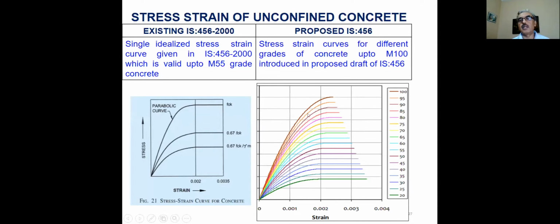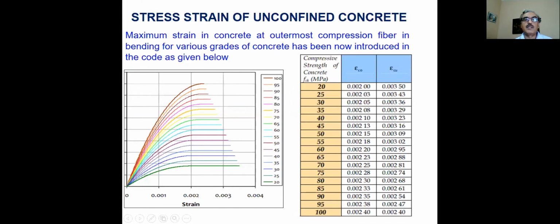If you go to M100, the curve becomes steeper, and there's not much difference between the peak and the ultimate, like we have here 0.002 and 0.003. There's a big gap for lower grades, but here at the top it is nearly matching. So keeping in view this range, for the lower grade we have the existing values up to M20, and then we are proportionally increasing it up to M100.